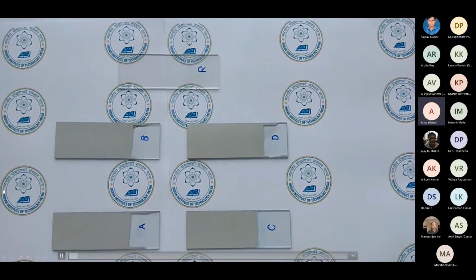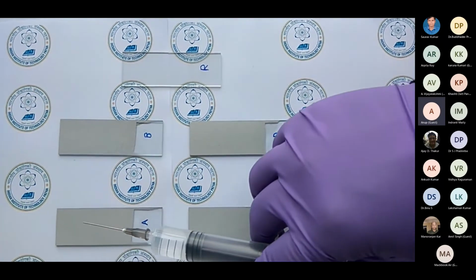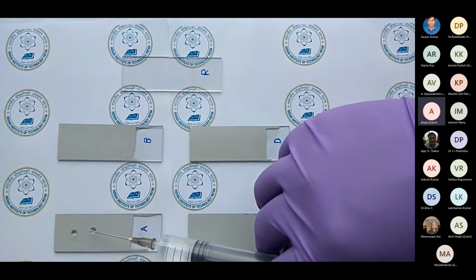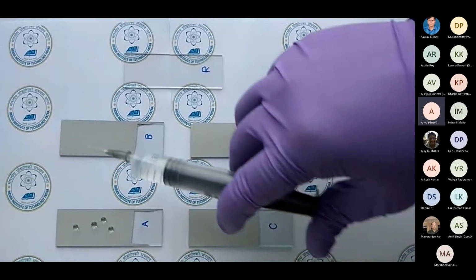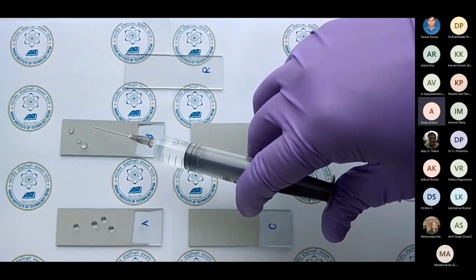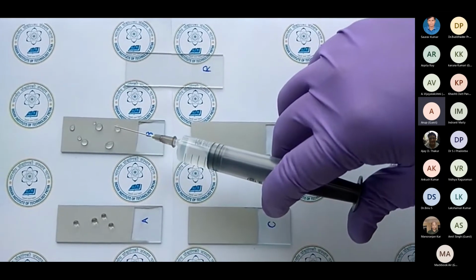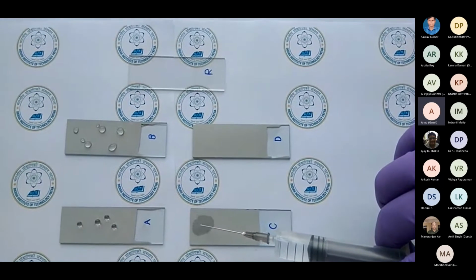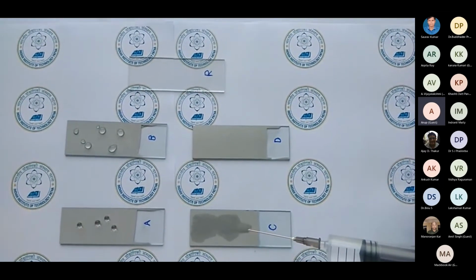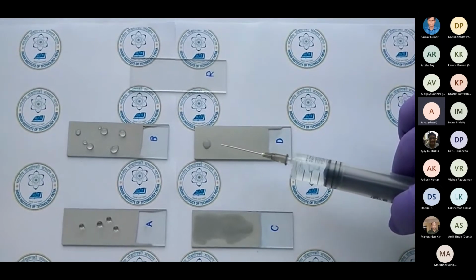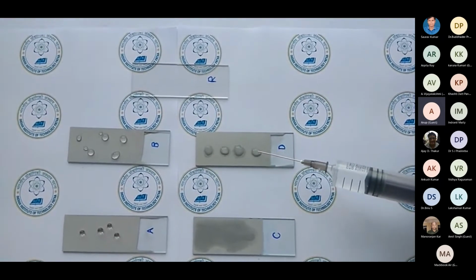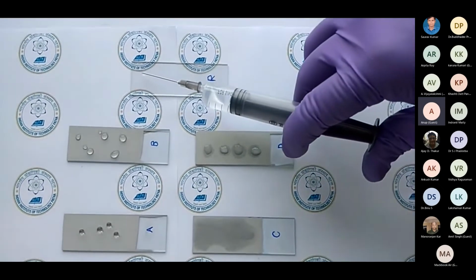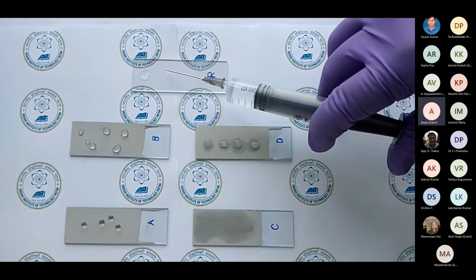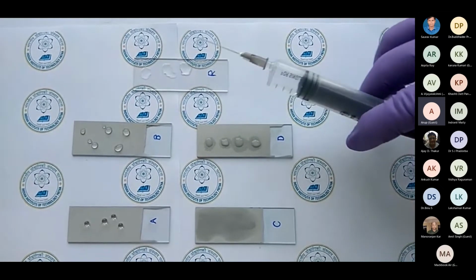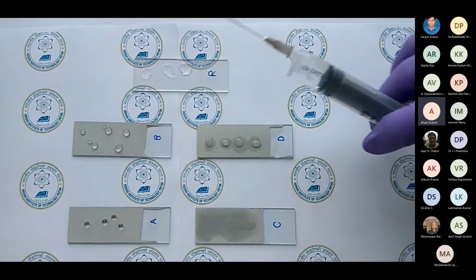Now let me show you the video here. If you are able to follow this, we are putting water onto this, so you can see the droplet of the water, how it is coming onto this substrate, right? You can see how the droplet is behaving over the glass substrate, over the coating. You can see here that C is completely super hydrophilic, the water has been completely absorbed, right? And image A is the super hydrophobic, right? The difference in all of this is only about changing the process parameter in the plasma, right? So you can see that by changing the process parameter, how the water droplet behaves on the surface.